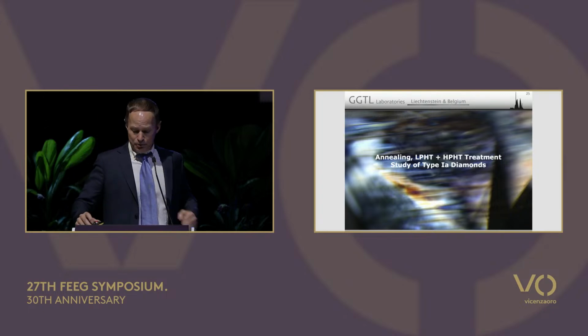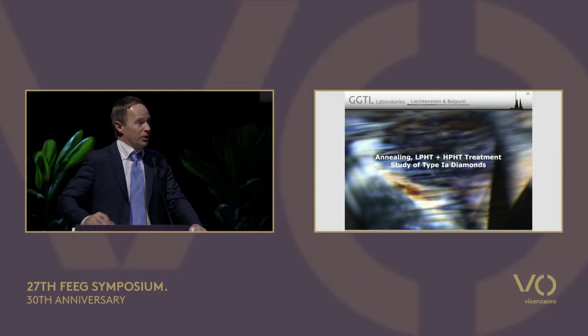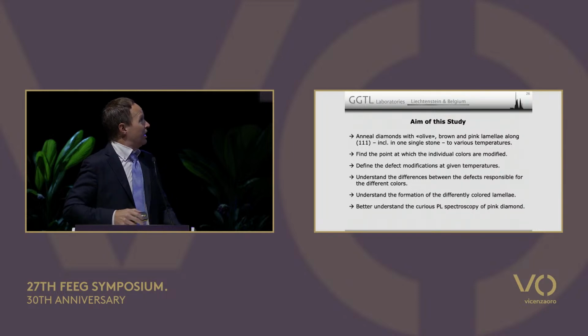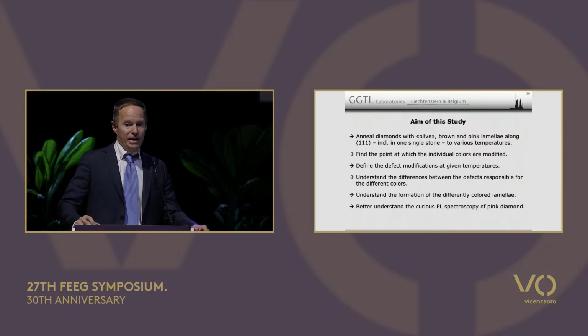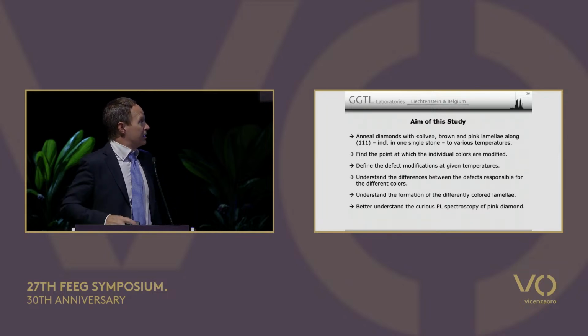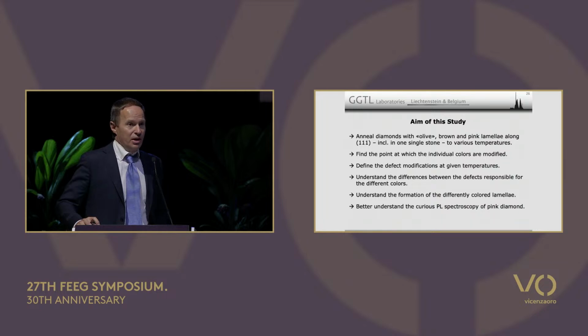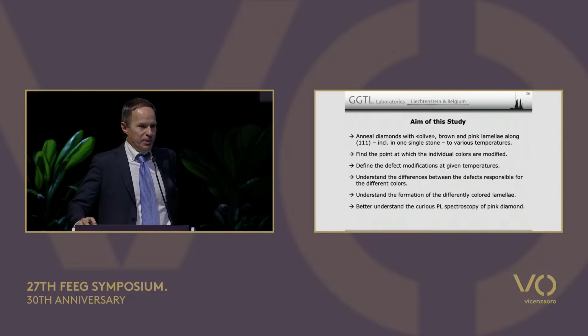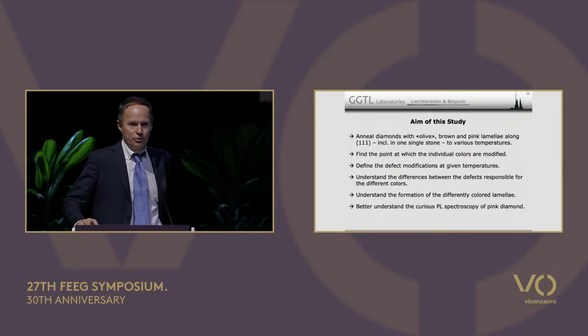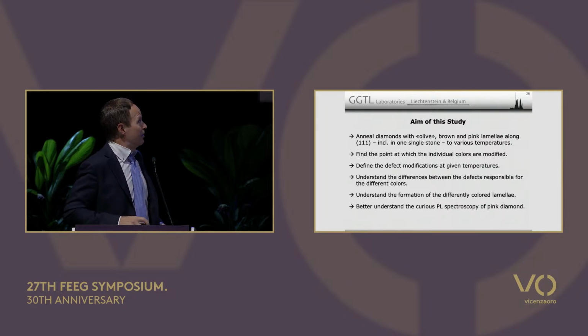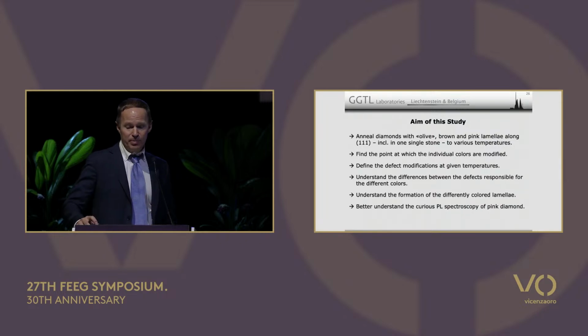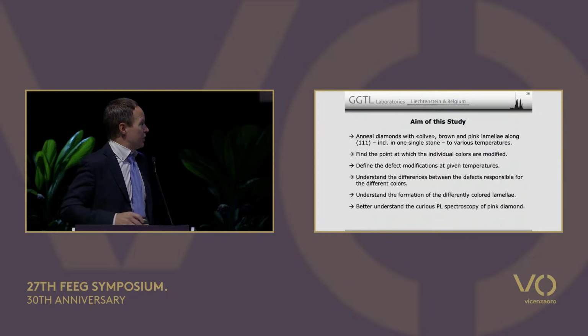Okay, so what did we do? We took stones that contain colored lamellae in all colors, and we treated them at different temperatures in our high temperature furnace. And then we went for HPHT treatment afterwards. But the first thing we did, we heated them up to 1500 degrees Celsius to see how they behaved and what happened in spectroscopy, what happened at which temperature.